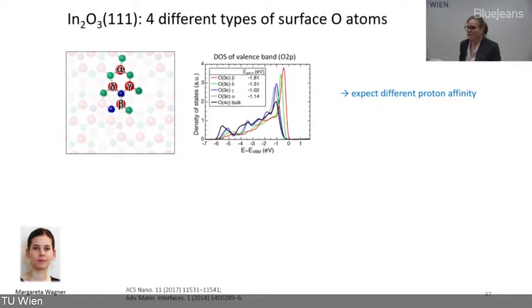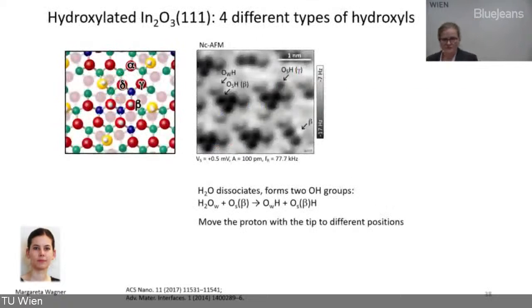That's what we want to probe with our force microscope. First we need to hydroxylate it, similar to what I showed before. Margareta exposed some water, which dissociated to form OH groups on the surface at special sites. She was then able to take a proton with the tip, snap it, and move it to different positions, making 4 different types of OH groups on this surface.